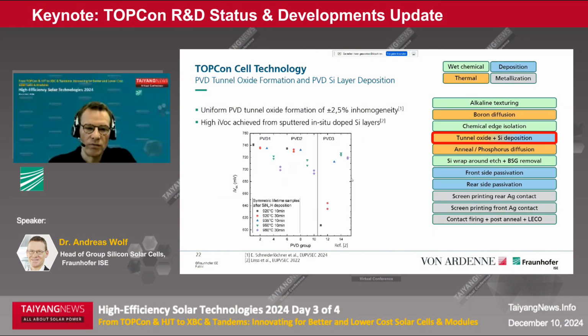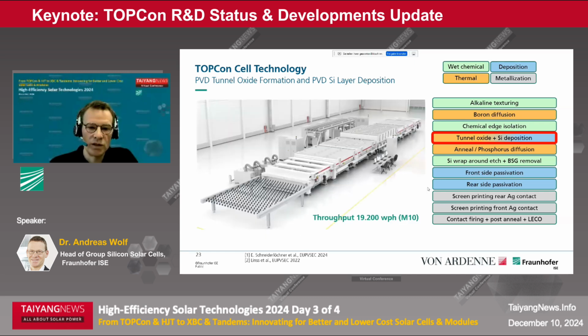When depositing the doped silicon layer by sputtering, it is also possible to achieve very high implied VOC values, like you can see from this publication. Up to 740 millivolts were achieved. And this means that sputtering is one option to deposit these layers, and it's also available to do this with industrial tools that feature very high throughput values.